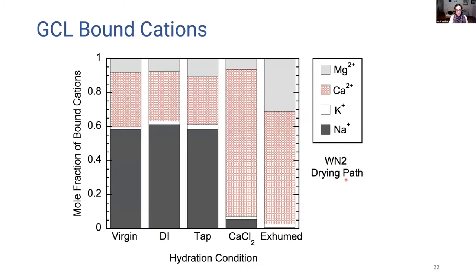The main reason for this is the changes in the exchangeable cations in the system. This is a graphic of mole fraction of bound cations versus hydration condition. We have the tests that we had been looking through in the earlier slides, deionized water test, tap water, calcium chloride, and exhumed material. And we have one additional data set shown here. This is for a virgin material. All of these tests are associated with the WN2 GCL.